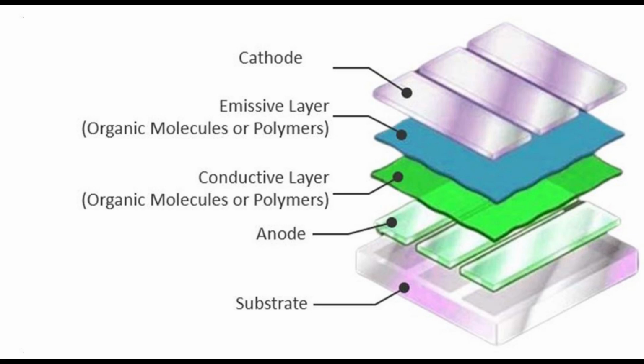TADF would allow stable and high-efficiency solution processable, meaning that the organic materials are layered in solutions producing thinner layers, blue emitters, with internal quantum efficiencies reaching 100%. Early in 2017, TADF materials based on oxygen-based fully bridged boron-type electron acceptors had achieved huge breakthrough in their properties. The external quantum efficiency of TADF OLED for blue and green light had achieved 38%, with thin full-width half maximum